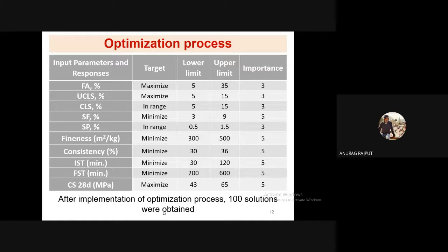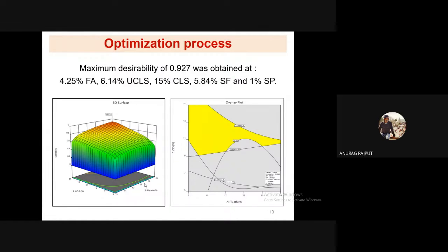Out of these 100 solutions, we have one best solution with the maximum desirability of 0.927, which is very close to 1. So this is the mix which can enhance all the properties, using 4.25% fly ash, 6.14% uncalcined limestone, 15% calcined limestone, 5.84% silica fume, and 1% superplasticizer. We can see that these dosages are quite different from what we input in the software. So this is the optimization process.